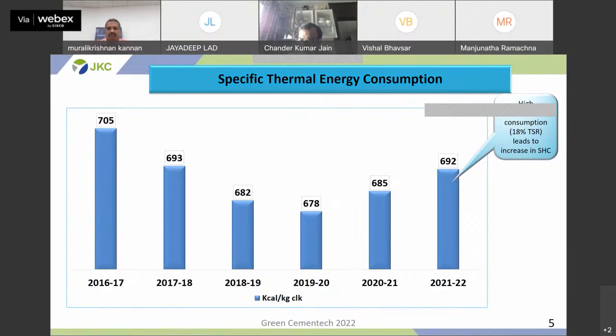of TSR, due to higher consumption of alternate fuel. As you know, by increasing each percentage of TSR, our specific heat consumption is increased by 4 kcal per kg of clinker. In spite of 18% TSR, we were able to manage our specific thermal energy consumption within